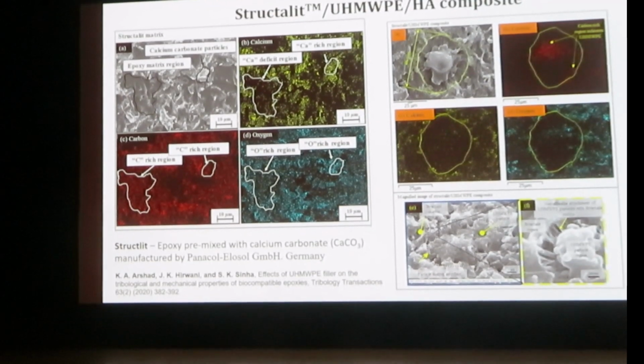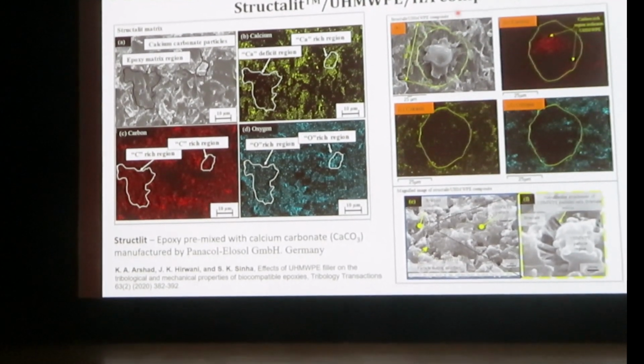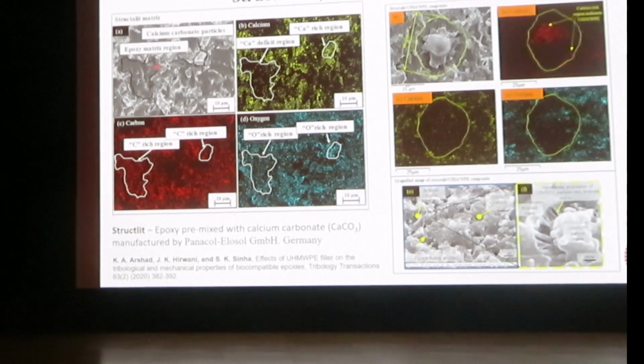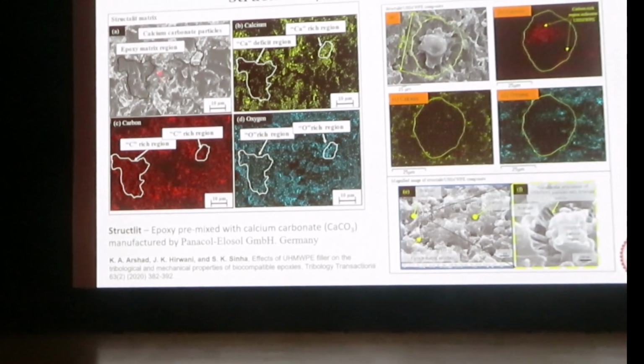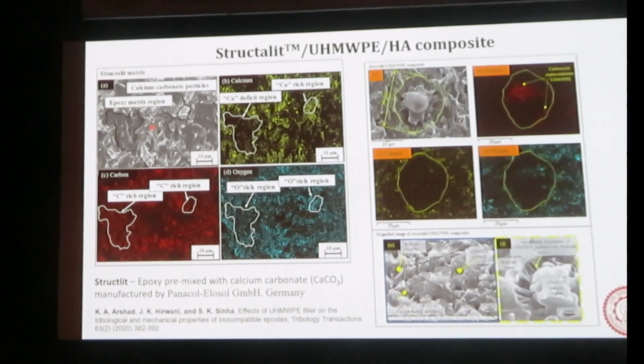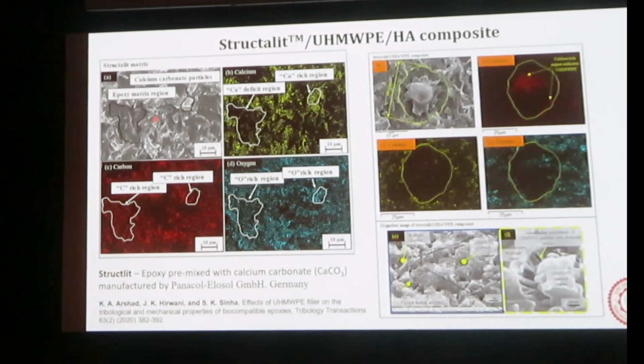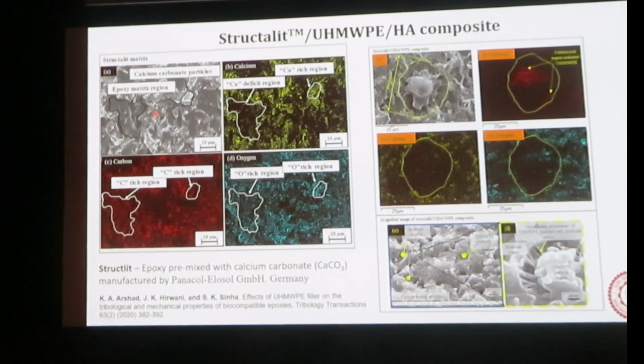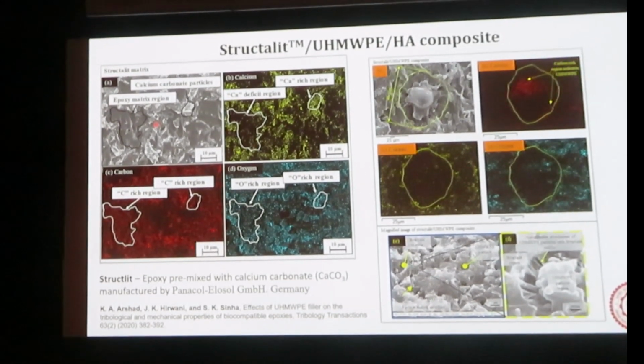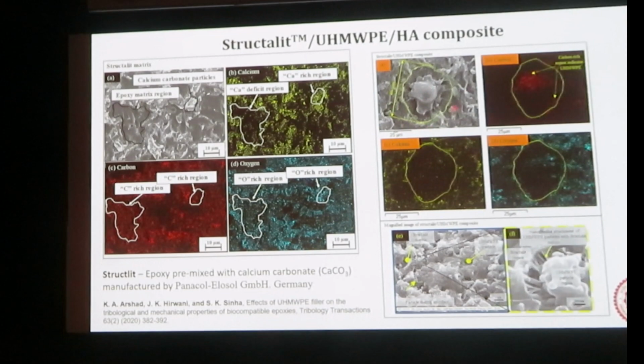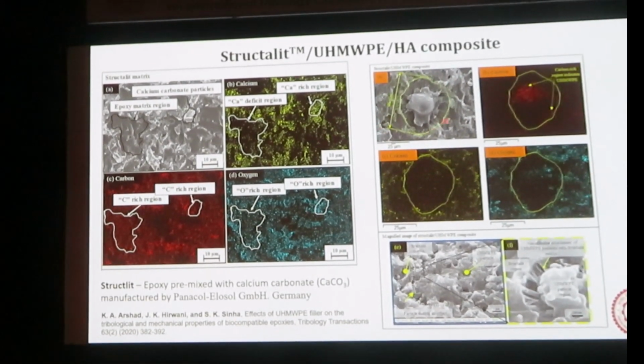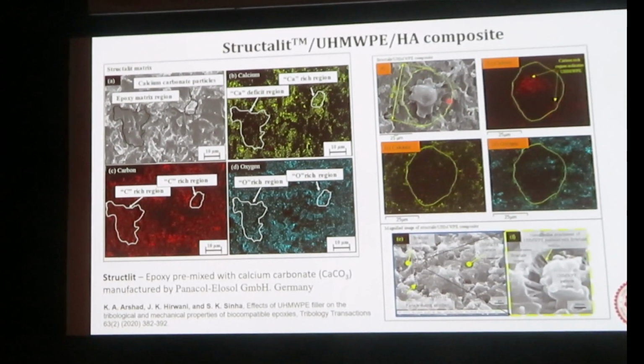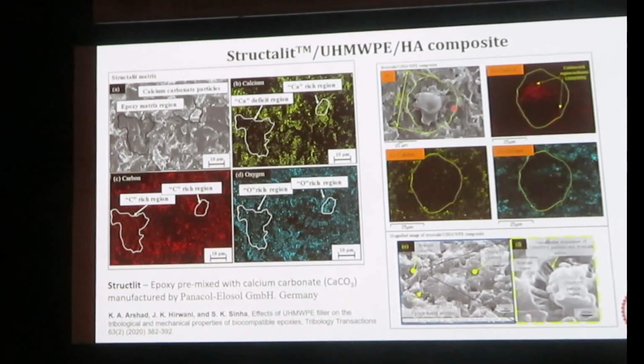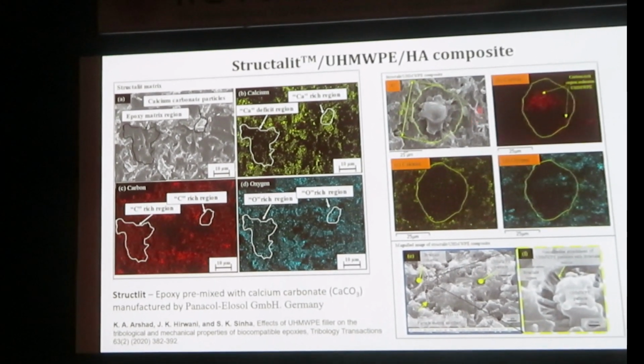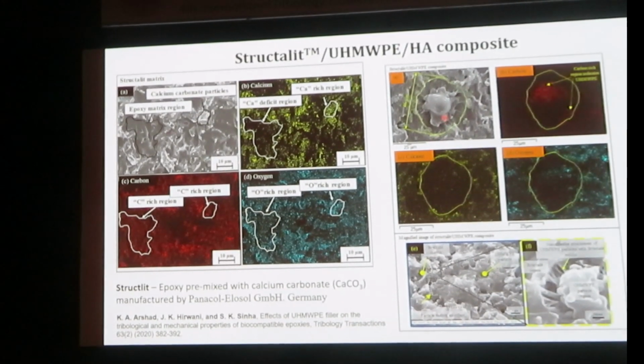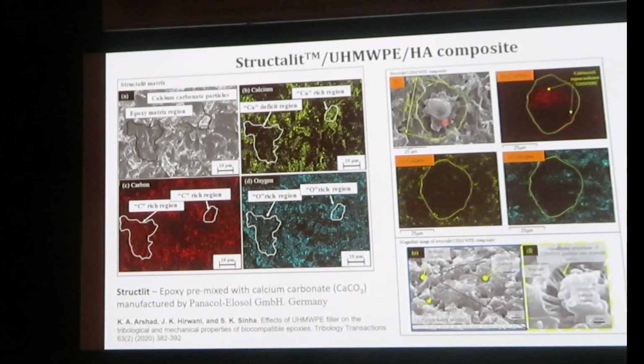And here again, we have used the UHMWPE particles and HA particles. This shows that they do have calcium carbonate, for example, calcium-rich areas we can see. And as you know, in tribology, calcium has a better effect in terms of friction and wear. This micrograph shows the bonding between the UHMWPE particle and the matrix, and it gives a very good bonding. There are no micro cracks, and the bonding is very good. That gives good promise for wear life.